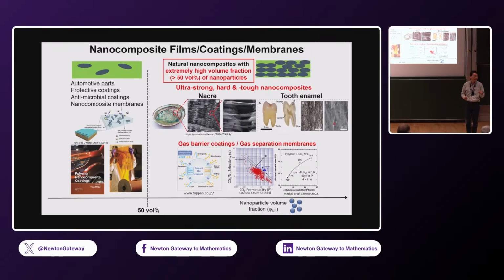The type of polymer nanoparticle composite that I'm interested in making are ones where the nanoparticle phase is actually greater than 50%. So the nanoparticle phase forms the majority phase. And the reason that this is interesting is illustrated in some of these natural composites that you see here. A lot of those natural composites have these cross properties. You know, they have high toughness as well as high hardness, which are two properties that are often in conflict with each other.